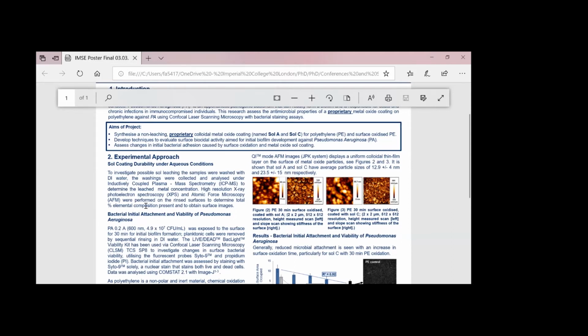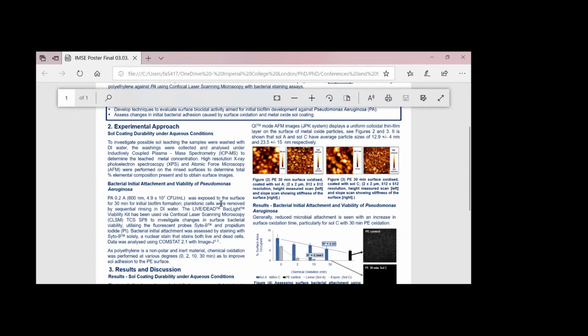Moving on to the experimental aspect of this piece of work, testing the sol durability under an aqueous environment is important as the assay is conducted in a hydrated setting with microscopy imaging. Seeing the extent of leaching is important as well. Inductively coupled plasma mass spectrometry was used to determine the metal concentration in water after sequential washes, and then XPS was used to determine the elemental composition.